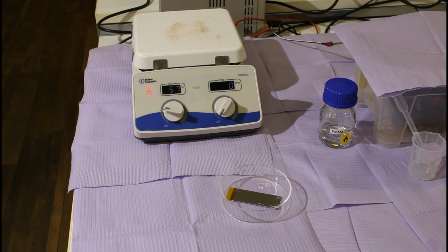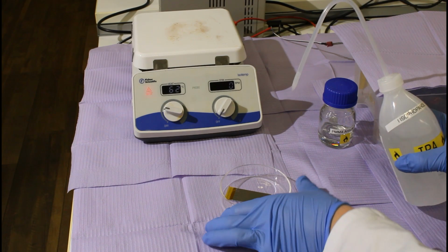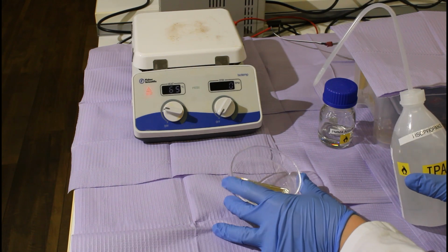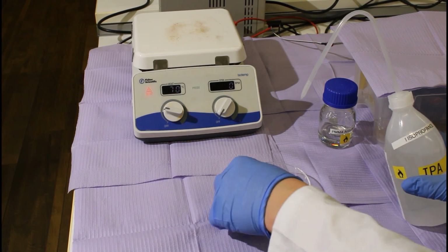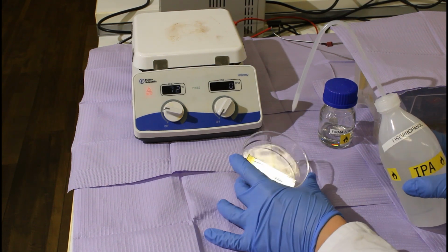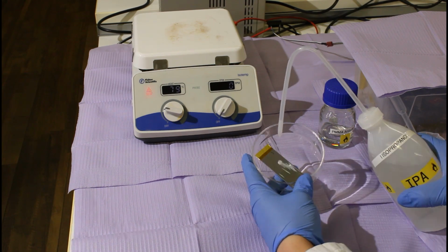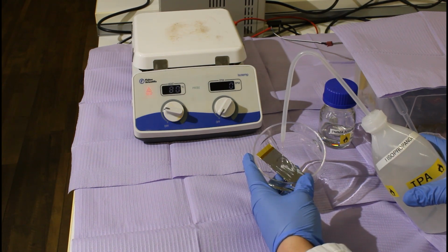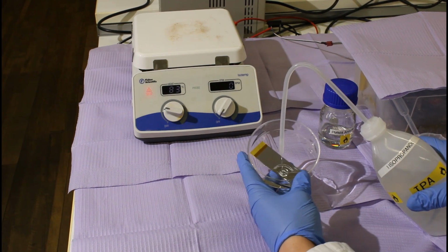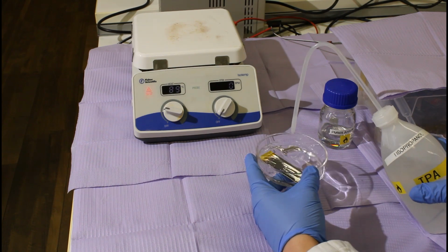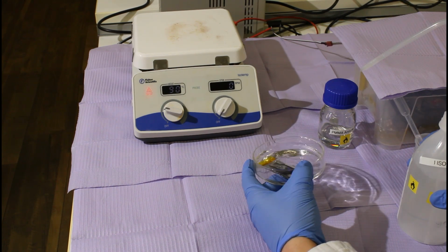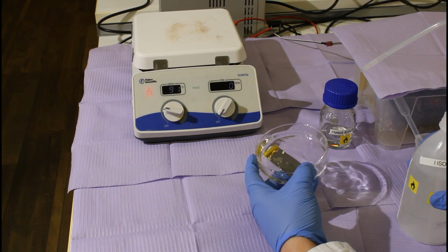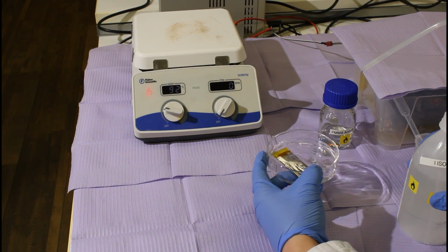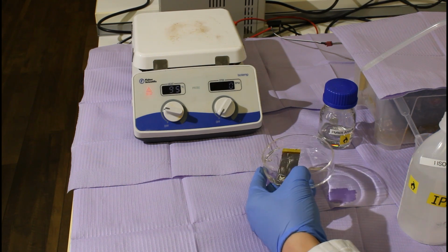The way this resist works is by the electrons cutting up the polymer chains. The fragmented molecules are soluble in isopropanol, while the unexposed resist is not. This means that developing it is just a matter of rinsing with alcohol, although there is a slight catch to this. If the area is heavily overexposed, it will actually start cross-linking with the rest of the chains. This means that the area will no longer be soluble in isopropanol nor acetone.